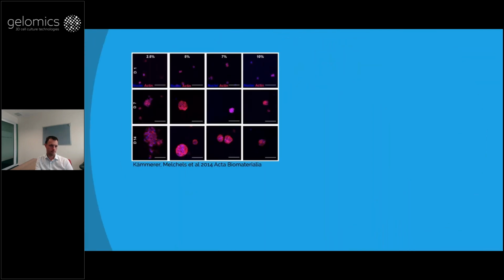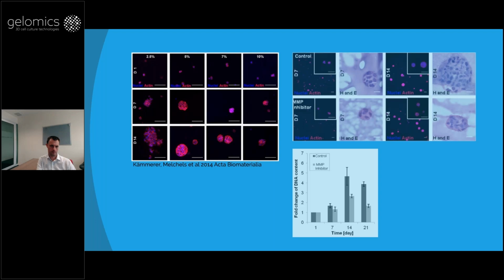Cancer models, this is back from the QUT days, the early days of using Gelma. So we used different concentrations, which means different stiffnesses, as we've seen before, and saw different behaviors. So if it's very soft, 2.5%, we see a bit of spreading in individual cells or a bit of chunks of cells. But at the higher stiffnesses, we see nice spheroid formation, which is a good model to test then cancer drugs on.